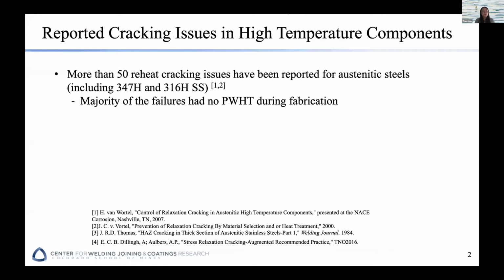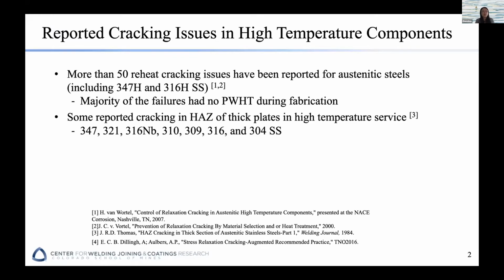Okay, so first of all, we have studied the literature and found that there have been more than 50 reheat cracking related issues in the austenitic steels that are designed for the high temperature working environment. So the materials include 347H stainless steel and 316H stainless steel. And the majority of those failures are related to the weldment that did not experience a post-weld heat treatment process. Also, there are some reported cracking issues in the heat affected zone of thick plates welded for high temperature service conditions. And a list of stainless steel materials is listed, for example, 347 and other typical stainless steels.